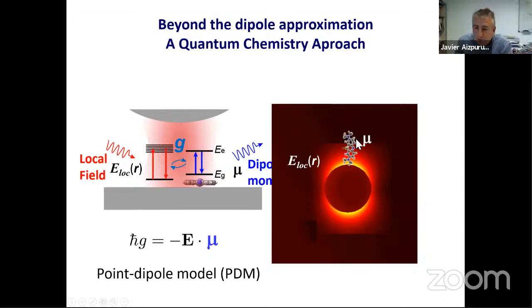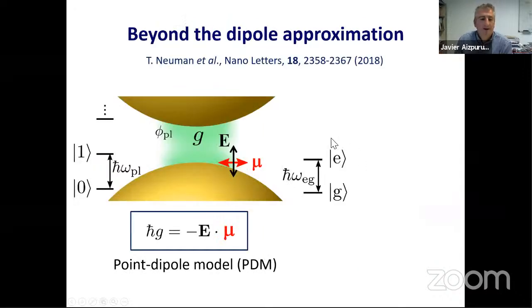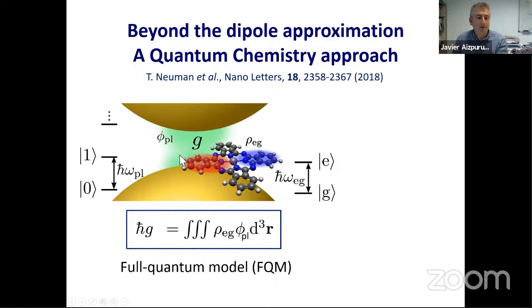And when you put, for example, this molecule here, that's what we want to do, right? This is again the point dipole approach. We have a point dipole mu in a local field, and we want to go beyond this. What we're going to do is substitute this point dipole by the actual distribution of electronic states of the molecule, in this case, this porphyrin. This rho of Eg is the transition electronic density between the excited and the ground state. This is the dipolar moment.